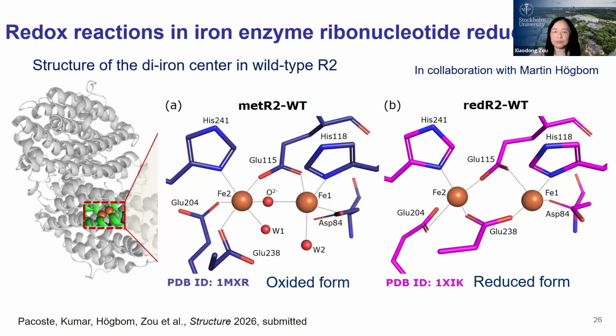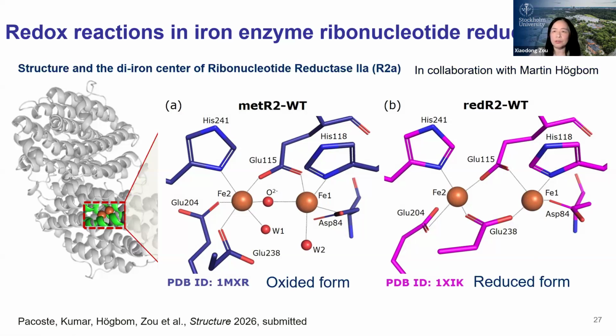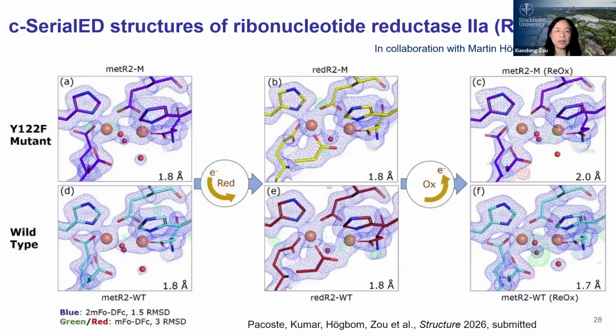This is the serial electron diffraction structure. If we compare the structures, we have the oxidized structure, we reduce the structure, then we reoxidize this structure. So that's the three different structures. As you can see, the reoxidized structure is similar to the oxidized structure. So that shows that we really can use electron diffraction to study this very well.